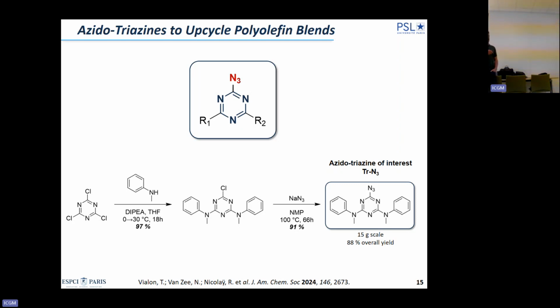So this is very available and inexpensive, and you go through an aromatic nucleophilic substitution, and you can introduce more or less any type of nucleophile you want. It's a very high yielding reaction, no need for column chromatography, and then in the last step, you introduce the azide, and you can make large-scale synthesis relatively easily. I see Jean nodding. I'm going to go back to the large-scale part, but you can make a good amount of molecule very easily.